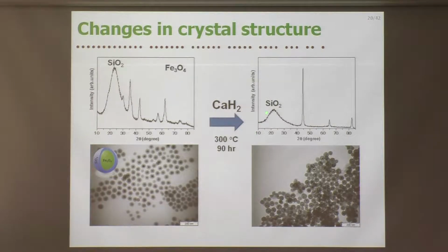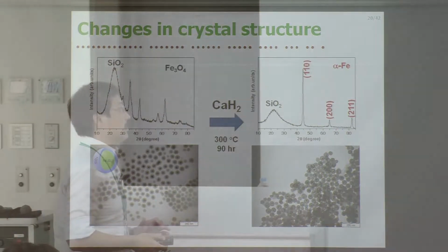Of course you can see the broad diffraction peak from amorphous silica, but now you can see only 3 peaks, all assigned to alpha-iron. So with these results, we can say we can get alpha-iron nanoparticles with well-defined morphologies.